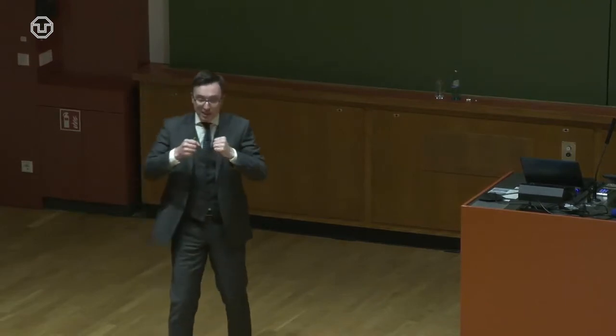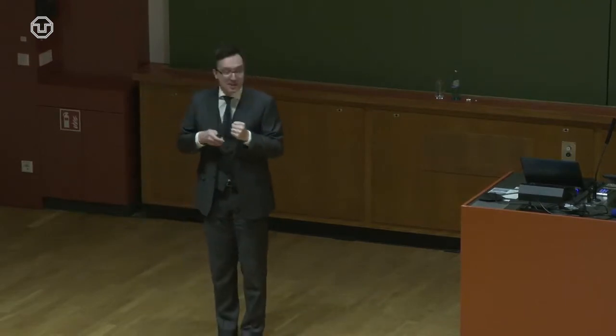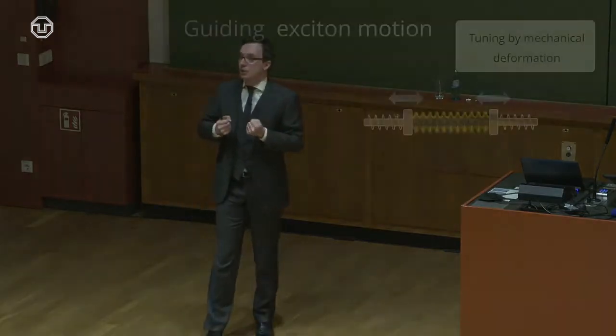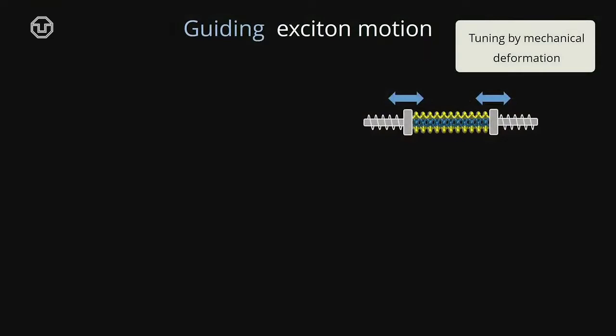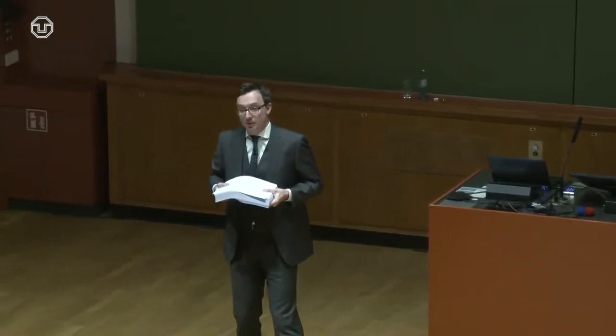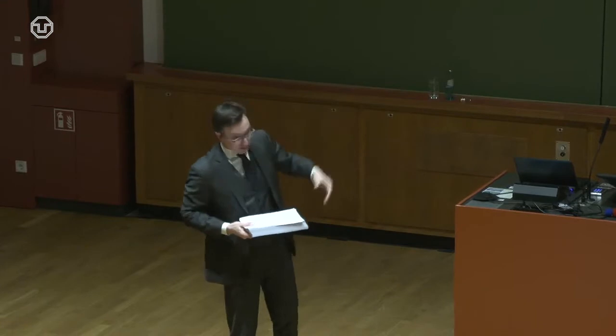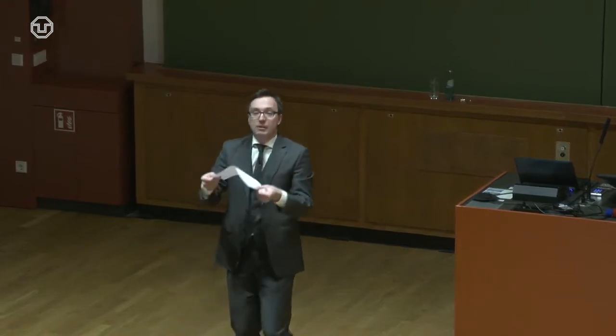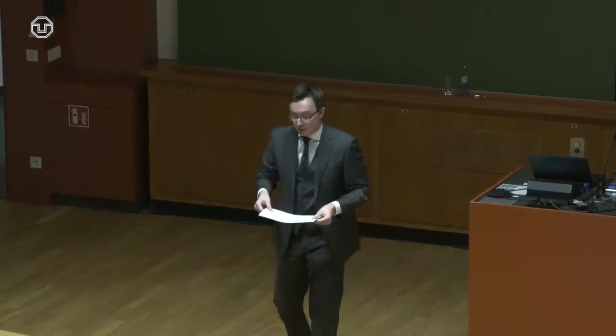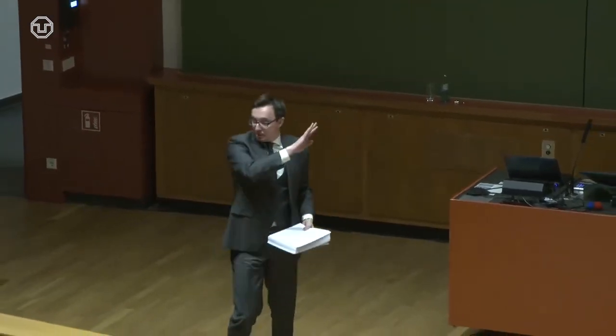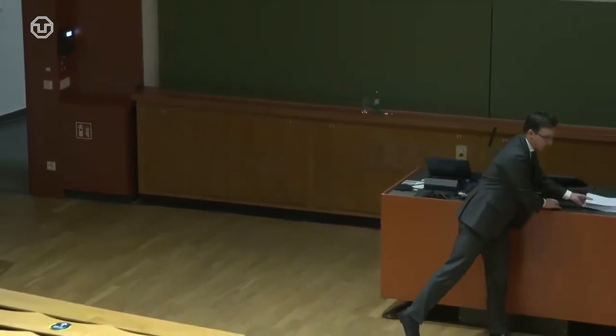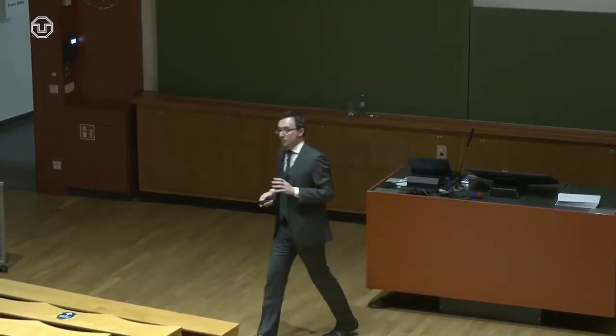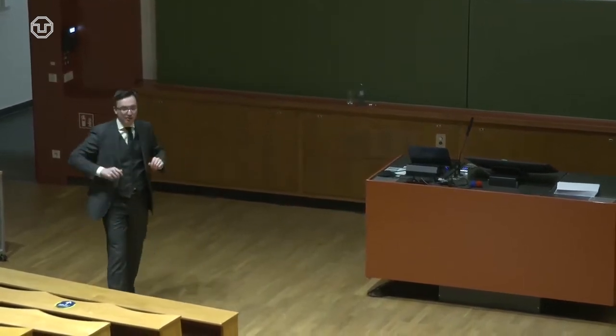But what we use here is a property that is also very specific when you make matter thin. Now you can do a lot of mechanical flexibility and use mechanical strain, mechanical deformation to create potentials, to create maybe guides for motion. And of course the principle, just to quickly demonstrate it: you take matter that is thick, and regardless of its properties, it will be relatively stiff, just by the nature of thickness. But those systems are very easy to manipulate, because if we just take one layer, now you can bend it, you can twist it, and what not. This applies for graphene, it applies for this type of systems. The mechanical deformation, strain as we call it, is a very powerful tool to create potentials, to create kind of energy landscapes.